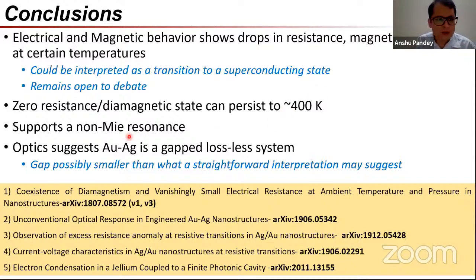And that is good. We see zero resistance, or apparent zero resistance, diamagnetic states, which seem to persist to 400 Kelvin. These materials also support non-Mie resonances, which to me are very interesting, more interesting than superconductivity, because this means the gap we are dealing with is apparently larger. But then we believe we have some explanation for it, that the gap might actually be smaller than what a straightforward DOS-based explanation might suggest.